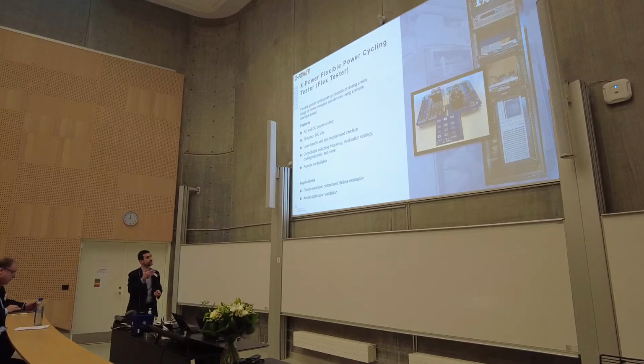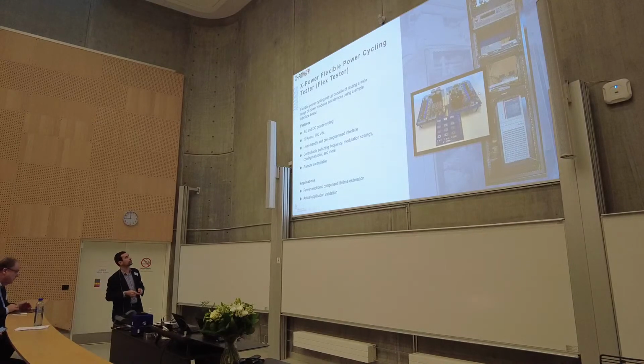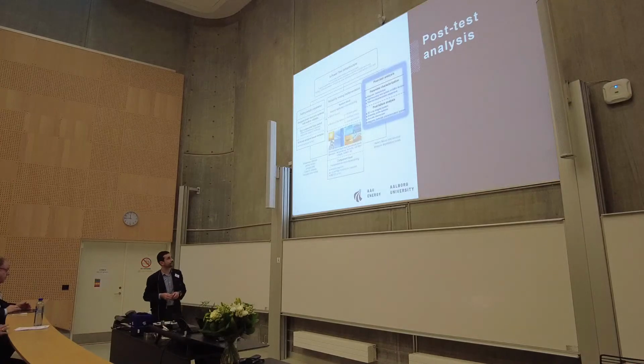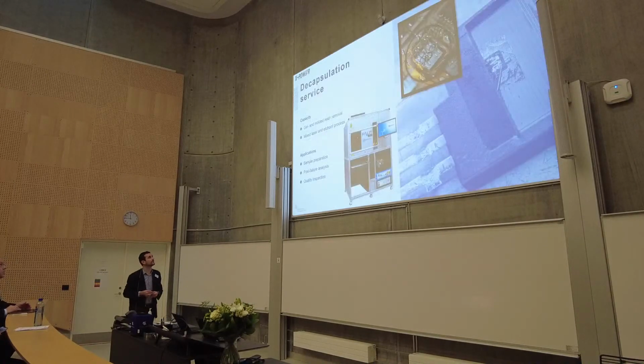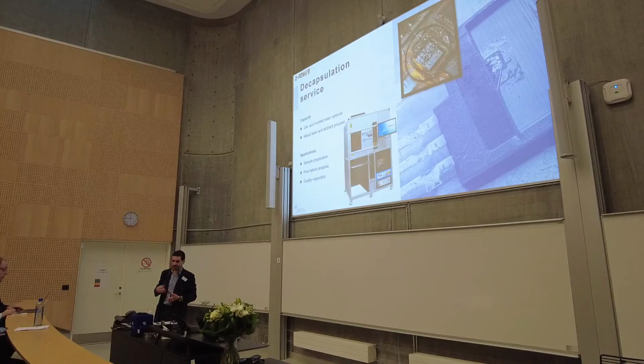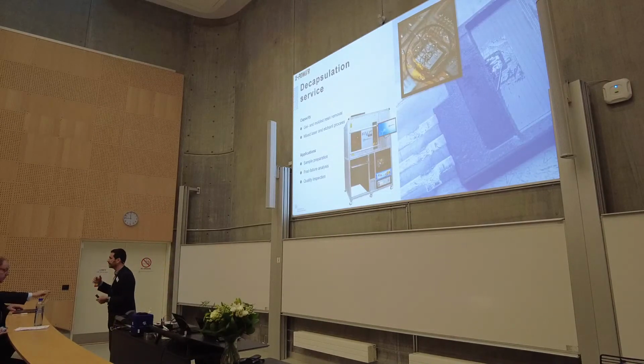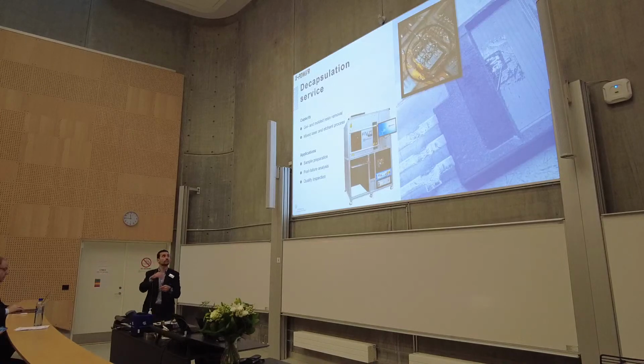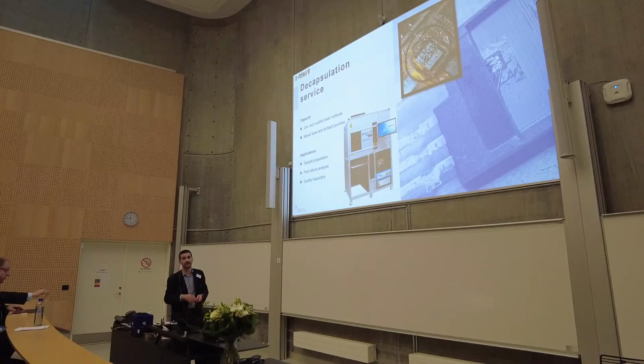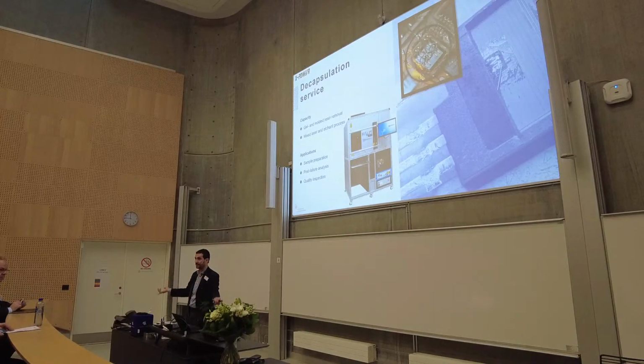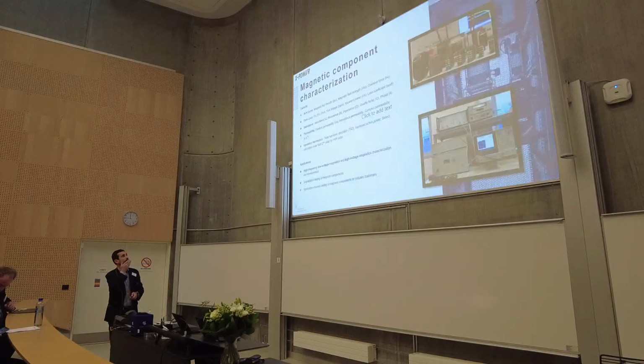We have a set of 6 channels here. This is a picture of one, and this is also something we are going to show you in the rest of the day. Very quickly about post-test analysis. Here we have a decapsulation service, which is basically a machine which is able to remove either molded modules resin, the black one, which is typically used for discrete components like this one in the background picture, or remove gel, very selectively, which is very useful for inspection, for working out what the damage of the single chip has been without affecting the rest of the module, without removing the entire gel from the module.